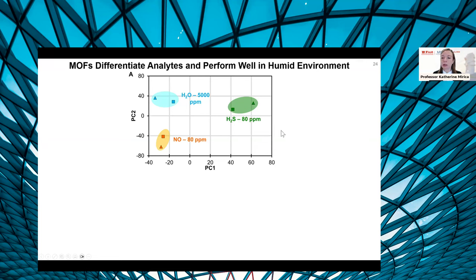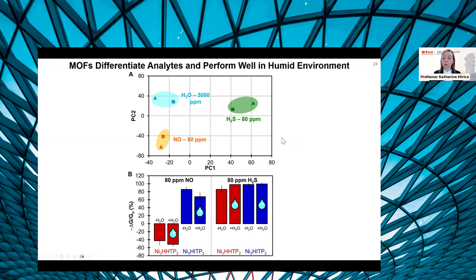But what's also important is that the sensor performance is uncompromised in the presence of humidity. So when we humidify our gas stream more than 10 times over the concentrations of the analytes that we're looking at, so this is all done at around 20% humidity, so close to 5,000 part per million concentration of water, we see that the performance is effectively unchanged in the presence of humidity, which could be useful for practical applications down the road.